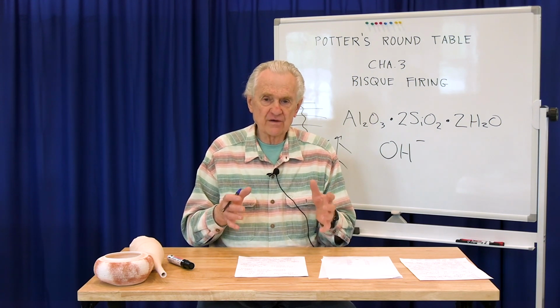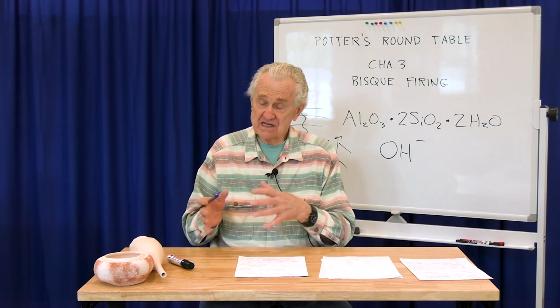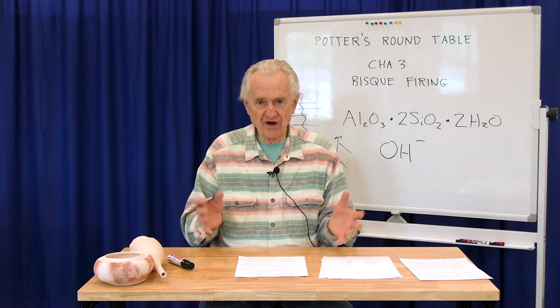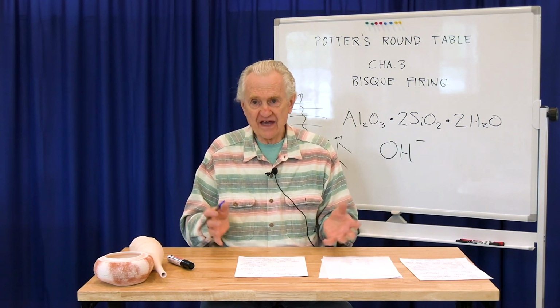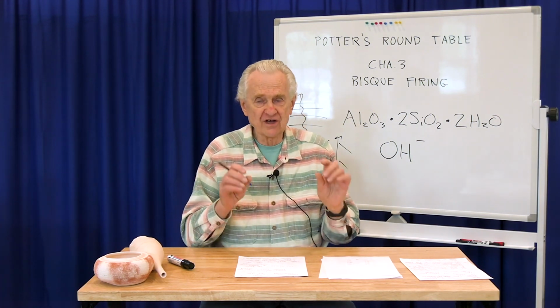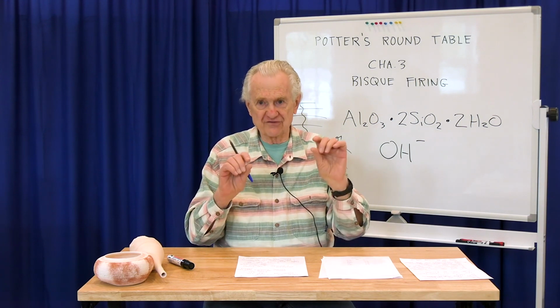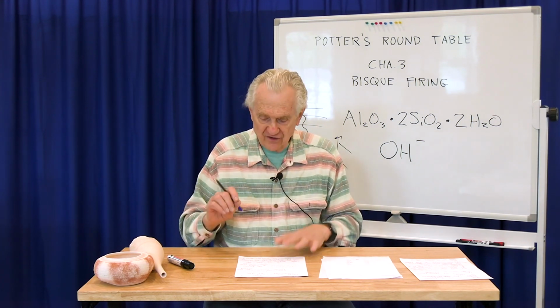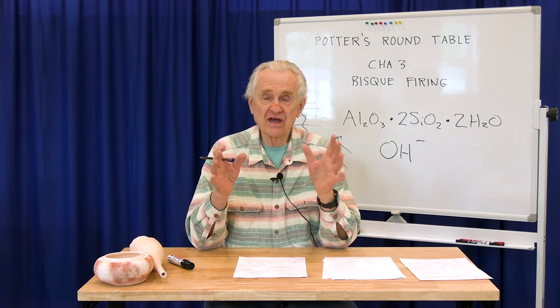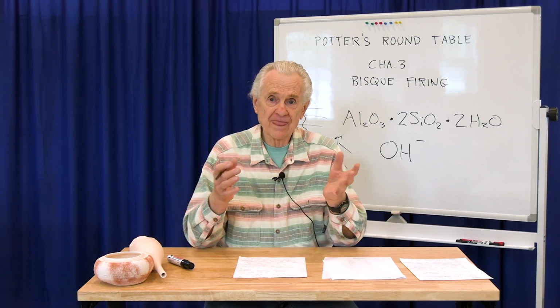Because if you don't get all the impurities out, what happens during the glaze firing is the impurities continue to break down and produce gas, and the gas bubbles up through the clay and produces two kinds of defects. Either pinholes, which are tiny little holes or bubble streams that come up through the glaze, or with maiolica, and this is particularly prevalent in a lot of maiolica, you get white spots in the colored areas.